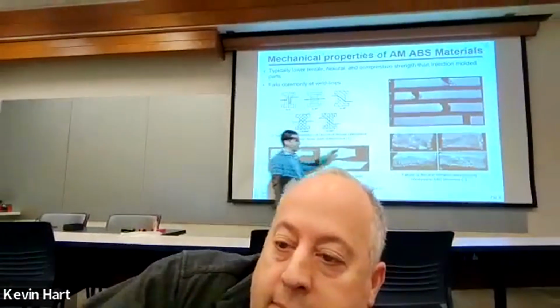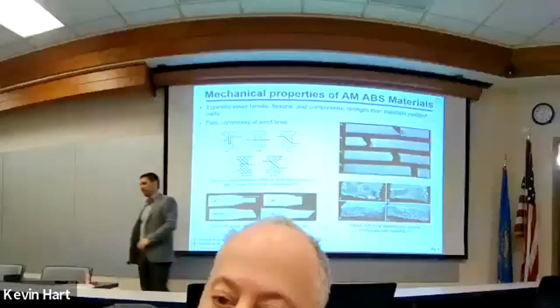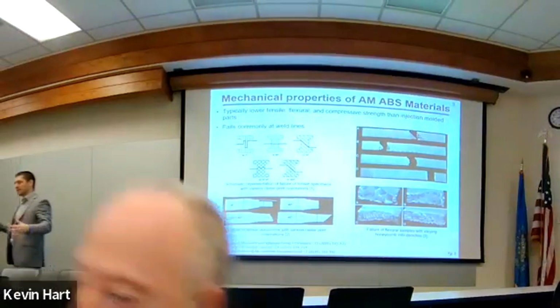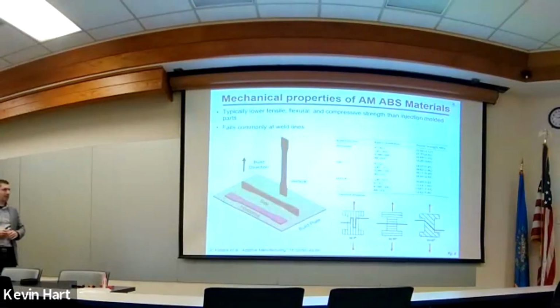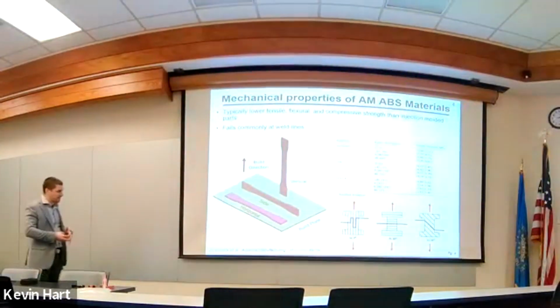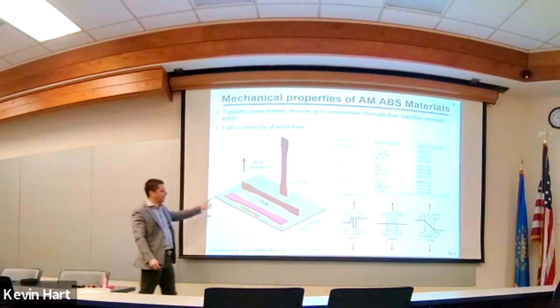So you can see that with dog bones printed with various raster angles. These are 4-point bend specimens that were tested in flexure, and you see a lot of failing at the weld lines, and it's pretty evident when you just look at this visually that that inner layer is particularly weak.